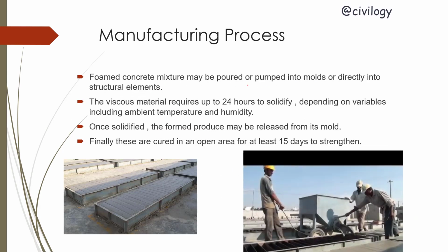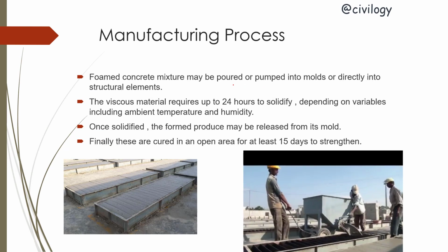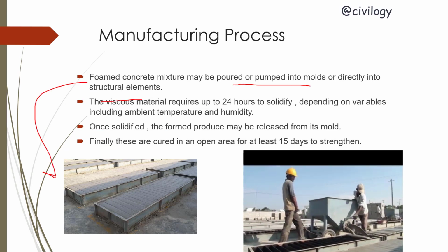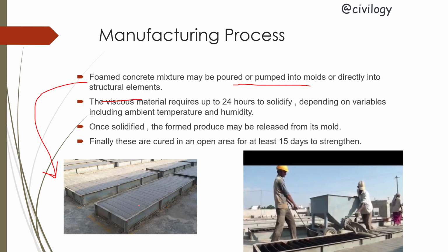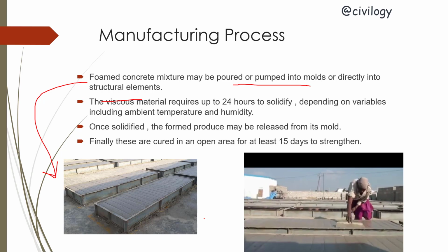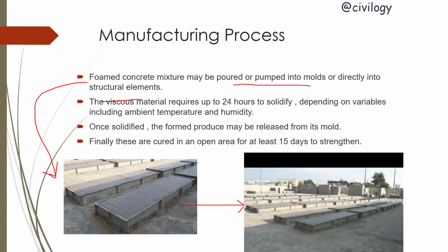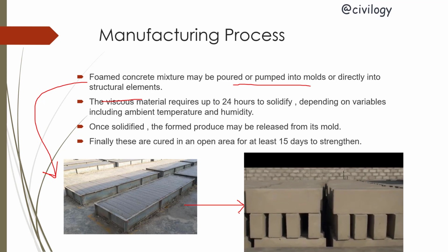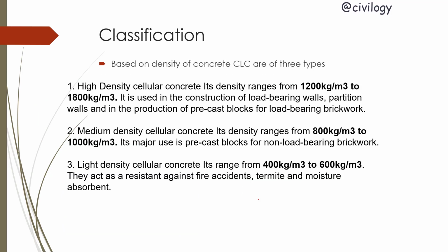This foamed concrete may be poured into molds or directly into structural elements. These are molds. This requires at least 24 hours to solidify. After solidification, the molds are removed, then transferred to the open area for curing, and it is cured for at least 15 days to strengthen.